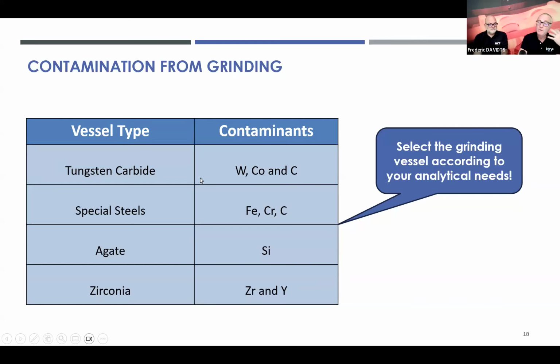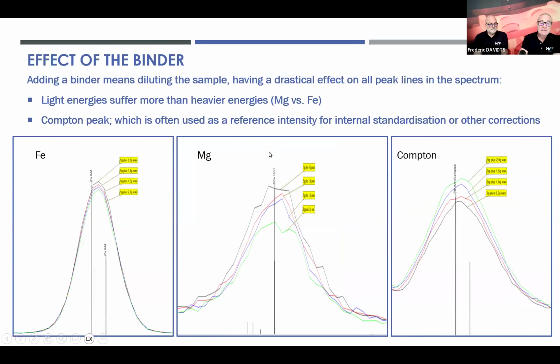We are not always aware that we contaminate, but contamination can also come from the sample that we ground before. If we grind, let's say, an iron ore, and the next sample is a quartz sand in which I want to analyze traces of iron, I would have a completely wrong story for the iron result if I haven't cleaned my vessel before.